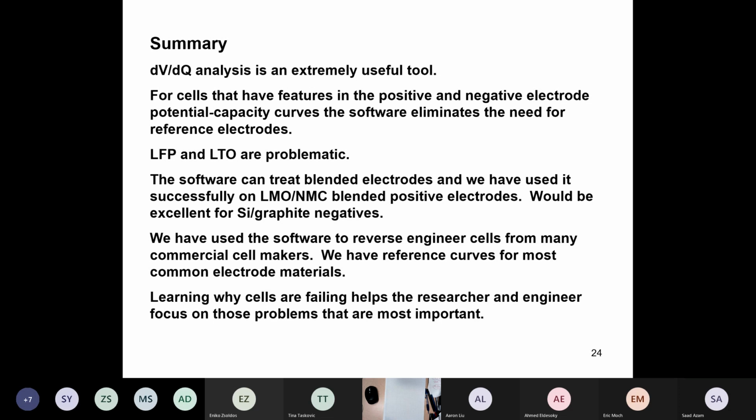That would come out. So in a situation where you have large volume change materials where there's a lot of active mass loss happening, you can help distinguish what part of the electrode is failing. But yes, generally the things you can get are the active masses and the inventory loss. That's all you can get.